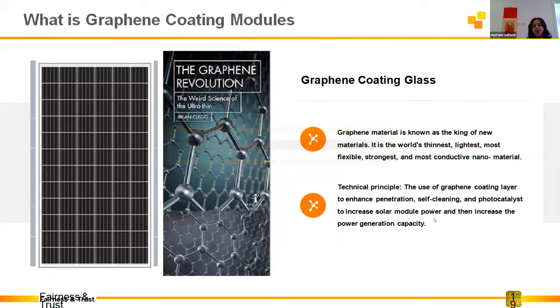Here you can see the graphene coating glass. Its material is known as the king: the lightest, most flexible, strongest and most conductive nanomaterial. The use of graphene coating enhances penetration, self-cleaning, and photocatalyst to increase solar module power and then increase the power generation capacity. Here, you can see the advantages, better transmission. Graphene coating glass has excellent high transmission properties. AM1.5 transmission equal to 94%, and visible light transmission is 94.2%. Here, the advantage is that it doesn't accumulate dust.